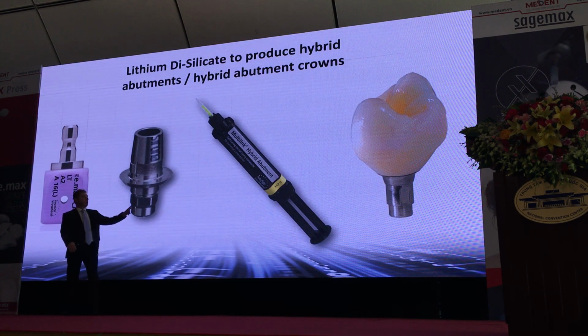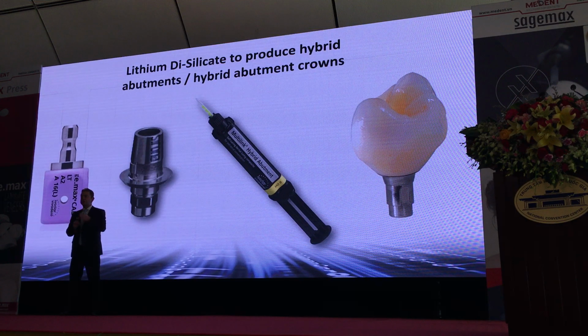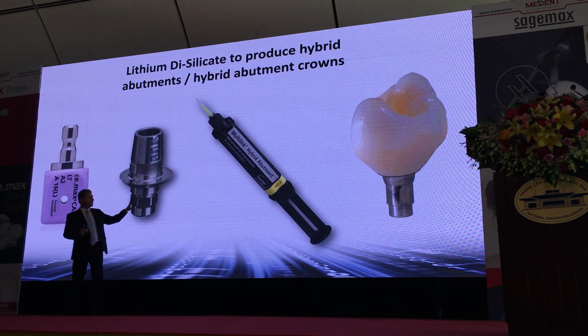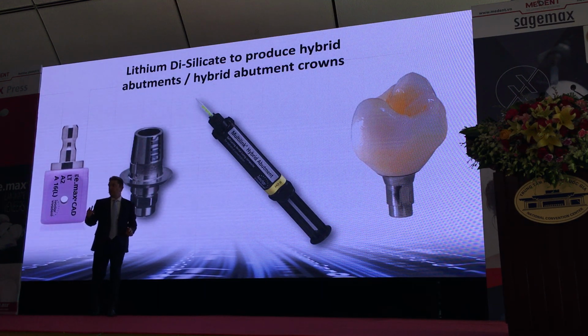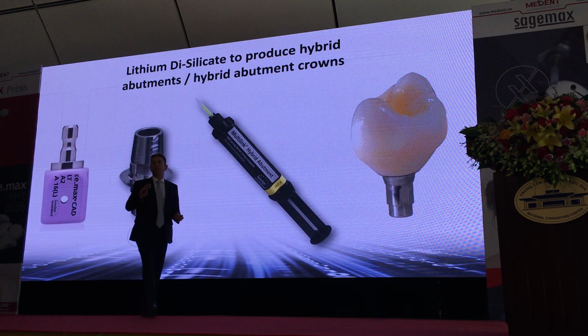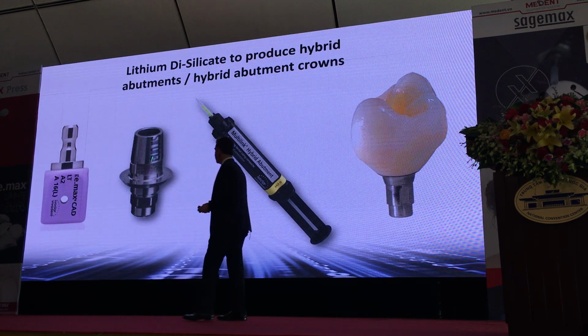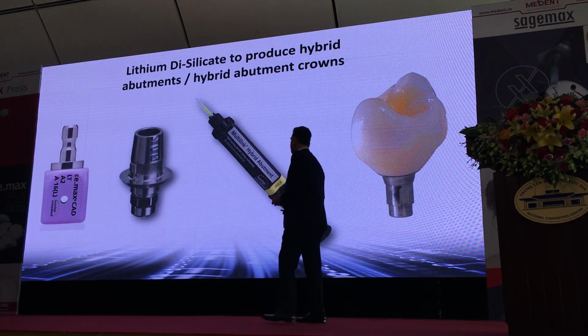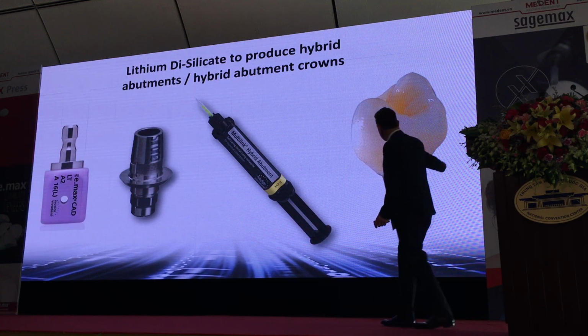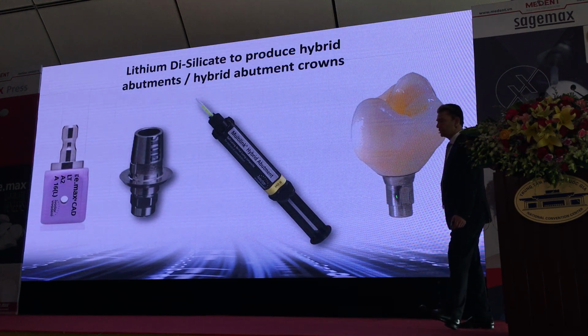If you use a cement which is not so opaque, then the titanium can shine through. You will see some grayish appearance underneath the crown. So this is important that we completely block out the titanium with that multi-link hybrid abutment, so that afterwards it really looks like this, looks really good.